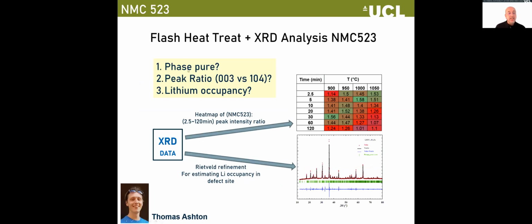So one of the things was, is it phase pure? This is actually an experiment where we're looking at temperature. What we've plotted here is the peak ratio of the 003 to 104. Now, this peak ratio is often considered in the X-ray diffraction pattern as a good indicator of whether you've got low cation mixing. What I really mean by that is you've got this layered structure with your nickel manganese cobalt in the blocks, and then between the blocks you've got these lithium ions that can diffuse.